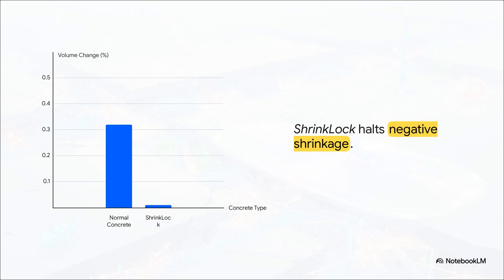Check out these numbers, because the contrast is wild. Normal, untreated concrete experiences a volume shrinkage of negative 0.32% as it dries, and that's exactly what tears it apart. But when it's treated with ShrinkLock, that negative shrinkage is completely halted. It actually induces a stabilizing microexpansion of plus 0.01%. It literally locks its own dimensions into place.